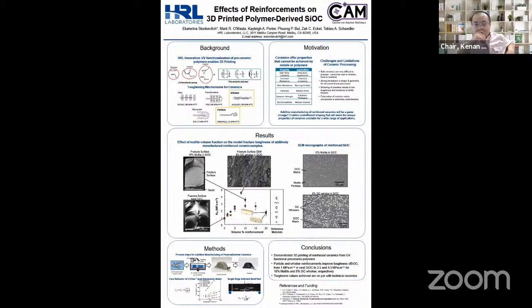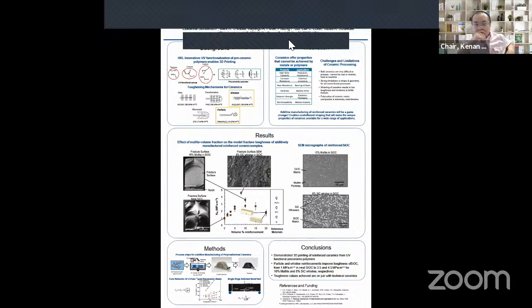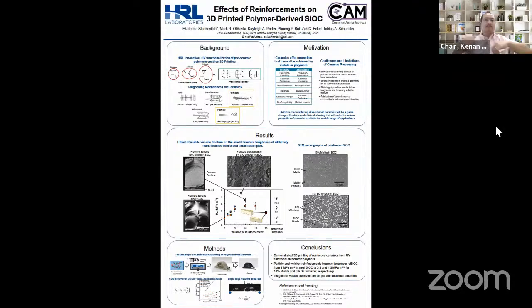In conclusion, we've demonstrated 3D printing of reinforced ceramics from UV functional pre-ceramic polymers. Particle and whisker reinforcements improve toughness of silicon oxycarbide from 1 MPa root meter in neat silicon oxycarbide to 3.5 and 4.5 MPa root meter for 10% mullite and 8% silicon carbide whisker, respectively. And the toughness values that we see are on par with that of technical ceramics.